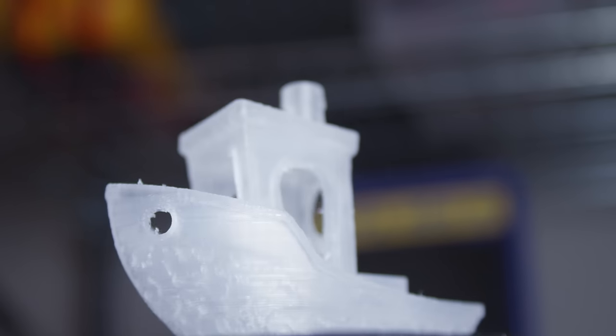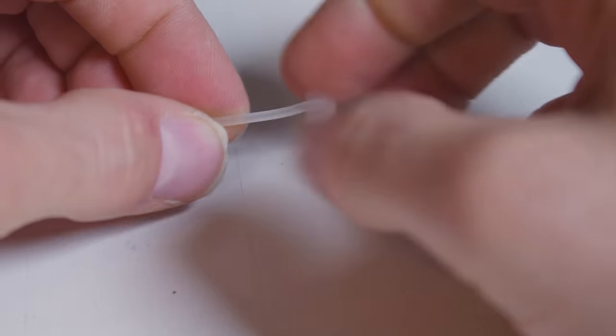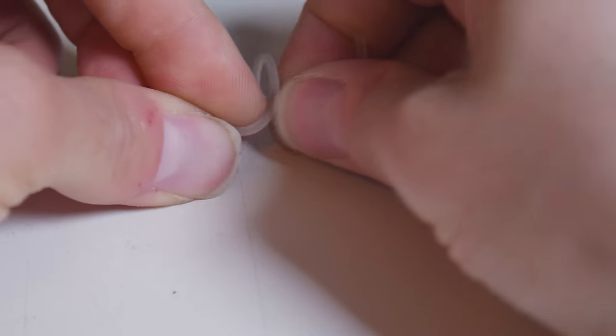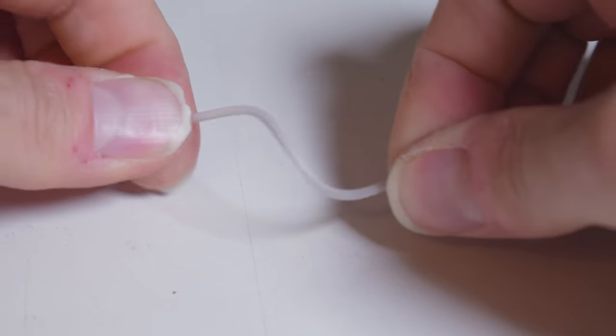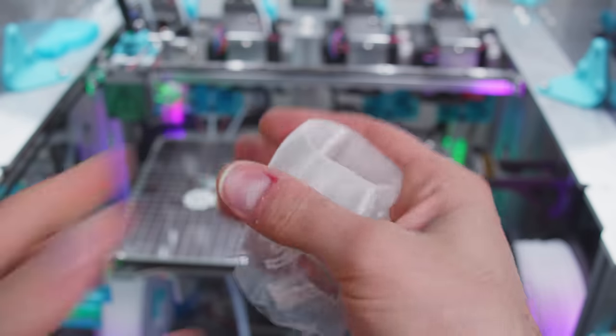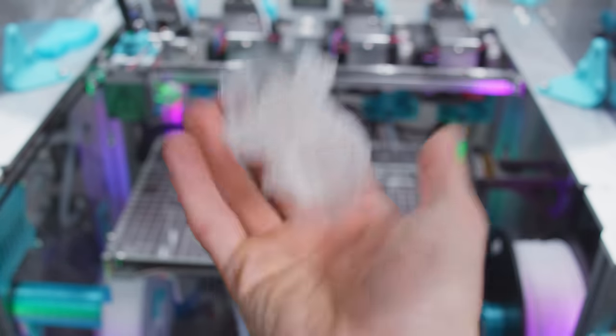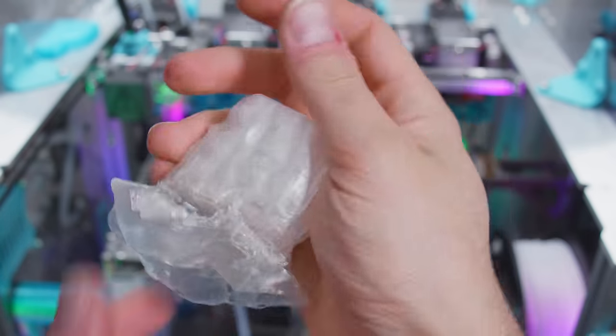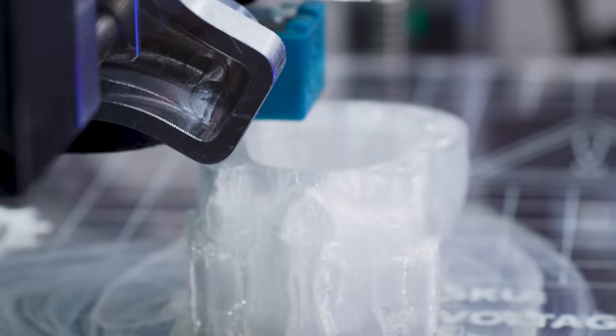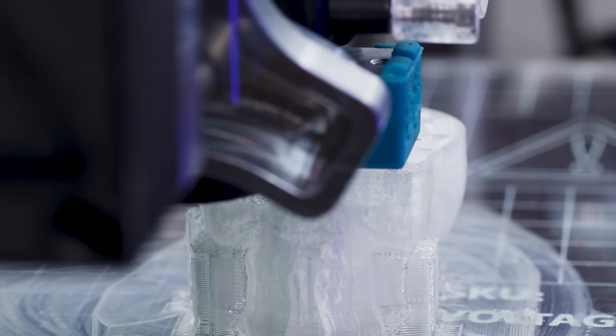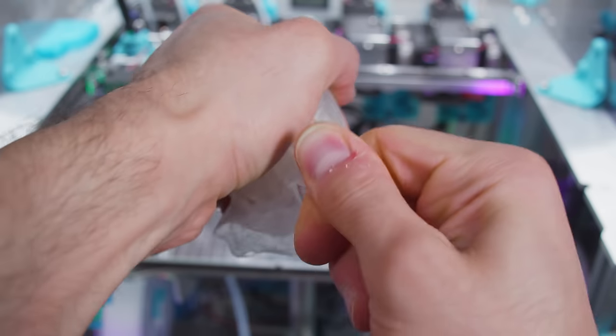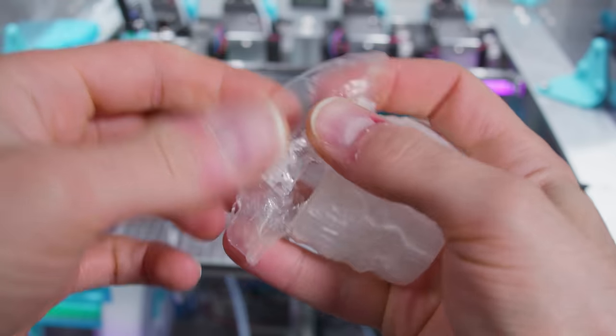This is all getting too positive. Let's regenerate our cynicism with the uniquely obnoxious Polypropylene. PP isn't just a funny pair of letters. It can bend without taking damage, it's extremely rugged, and its phenomenal layer adhesion and tensile strength make even single wall vase prints effectively invincible. It's also the lowest density filament, so prints feel feather light and you get like 30% more filament per kilo. But Polypropylene does not appreciate being printed. First, PP has some of the worst bed adhesion. Then, Polypropylene is more curly than a three stooge, and the warping actually gets worse when it cools. Like TPU, PP has perfect layer adhesion, but it's so much tougher it makes supports impossible to remove. At 40D durometer, this PP is far softer than any TPU, so you can't make the most of its strength. I'm sticking my PP in F-tier.